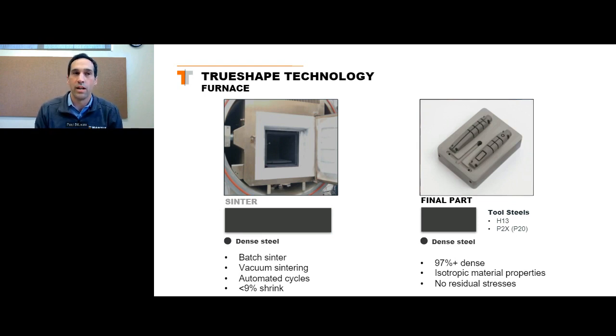And inside the sintering furnace, we elevate the temperature to just below the melting point of the steel, so it's a little less than 1400 degrees Celsius. In that process, the metal particles all fuse together. That trace amount of binder or glue is removed. And as the part cools off, as the tool cools off, it turns into dense steel and takes on the properties of, for example, H13. So our H13 steel is chemically equivalent to any other H13 steel. The only difference is it starts its life as a paste, which allows us to print it and shape refine it when it's in a very soft state. And then when it turns into steel, it's durable tool steel, just like any other H13 steel.